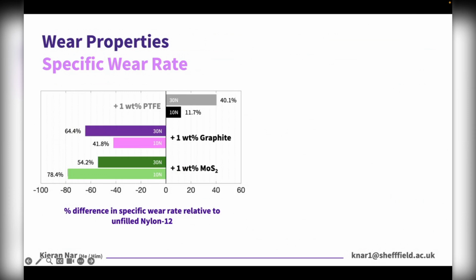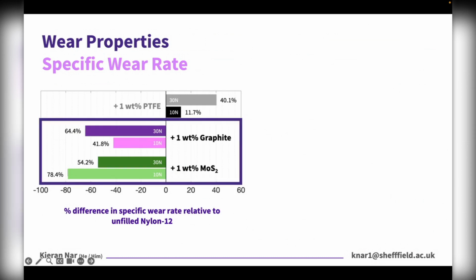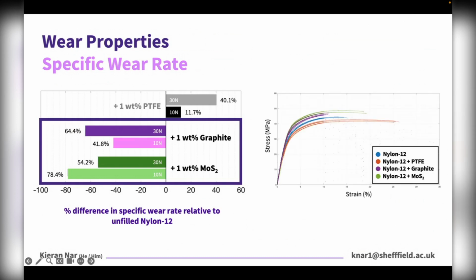And when we look at the wear results collected, we found the opposite to be true. So the addition of PTFE increased our wear rate, whereas the addition of graphite and molybdenum disulfide rather significantly reduced the amount of wear incurred during sliding. And we found this to be linked to the mechanical properties of the parts produced, specifically strength and stiffness.